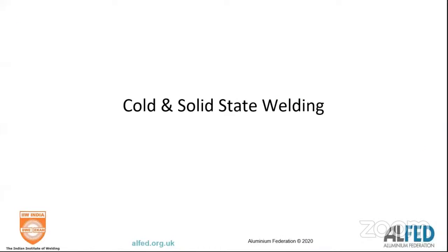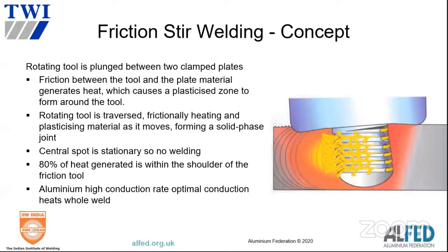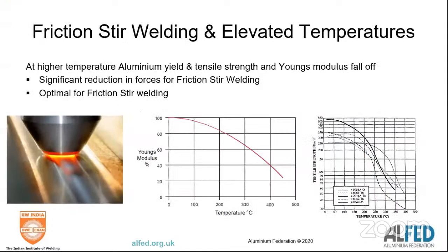Just looking outside the box for a few minutes, there's a lot of work going on in solid state welding and cold welding, and the Welding Institute is world champion in friction stir welding, invented, championed, developed. In essence, with friction stir welding, a tool is spinning round, it's plastically moving the metal, and you've got very localized heat production, which is great because it means that you're overcoming the high conduction rate of aluminium. And the beauty of aluminium in terms of friction stir welding is that at high temperatures, Young's modulus drops off, it becomes more and more plastic, and mechanical strength falls off. So aluminium is actually perfect for friction stir welding.